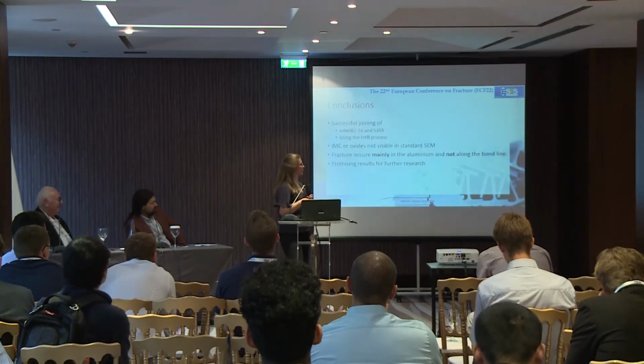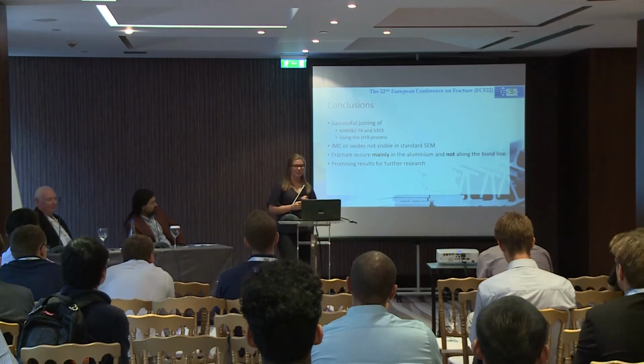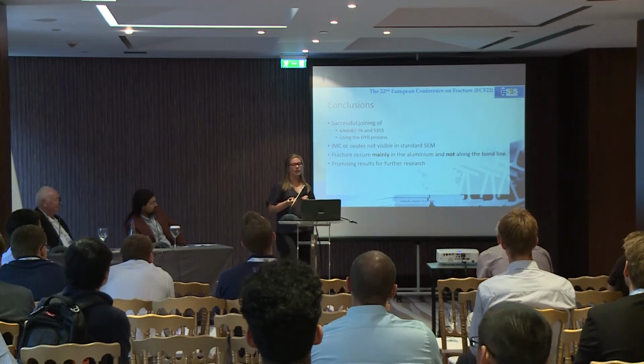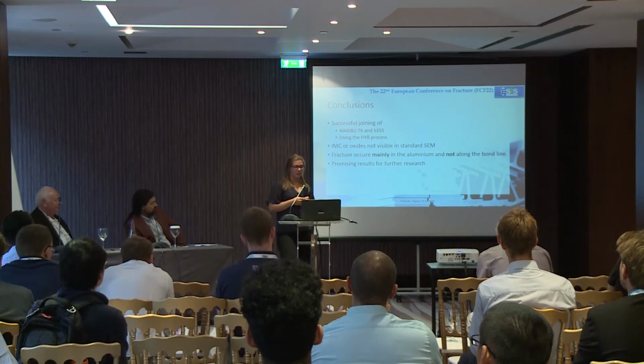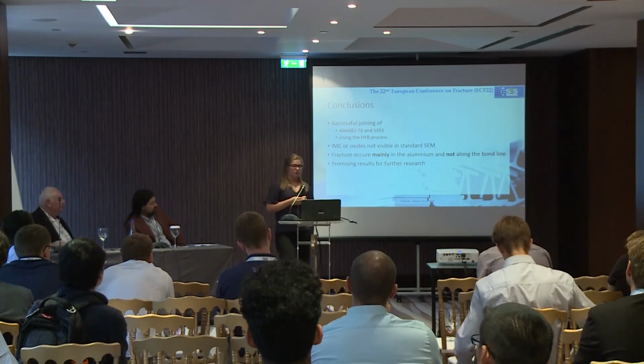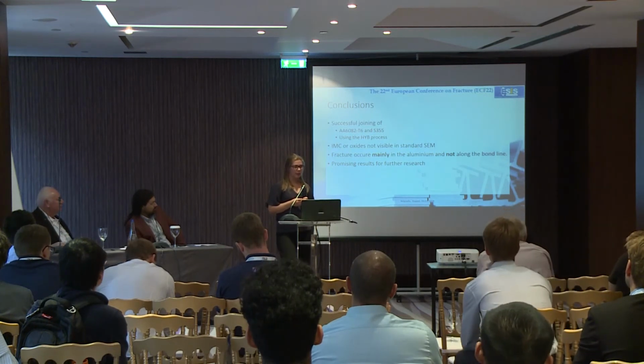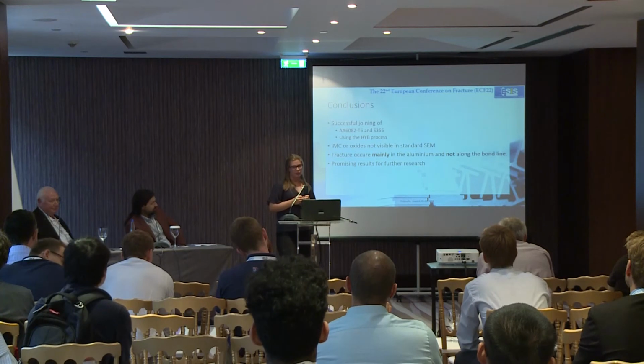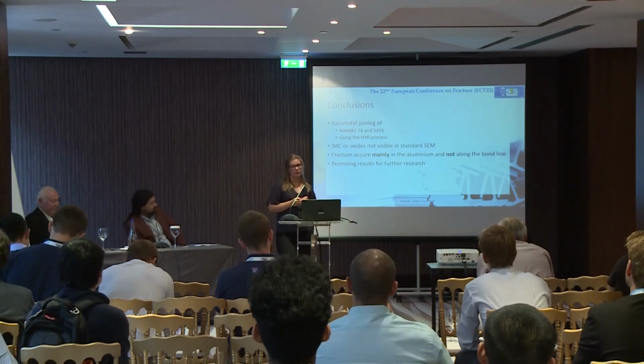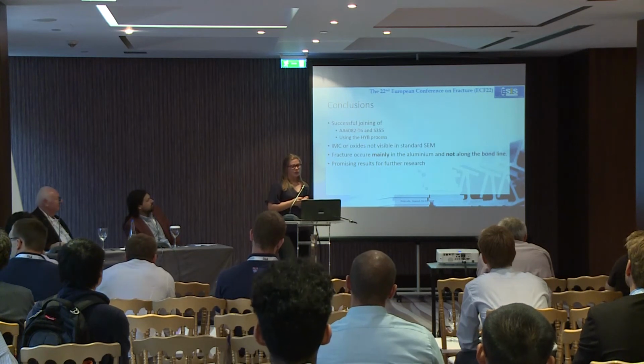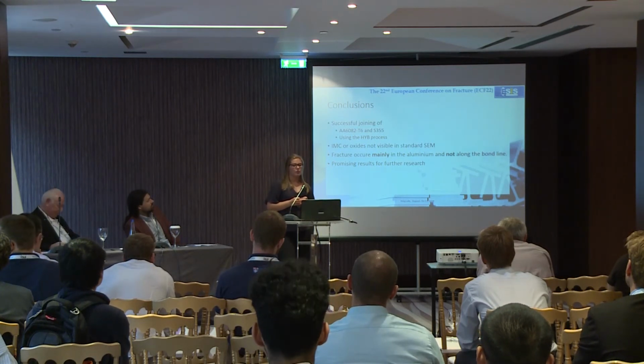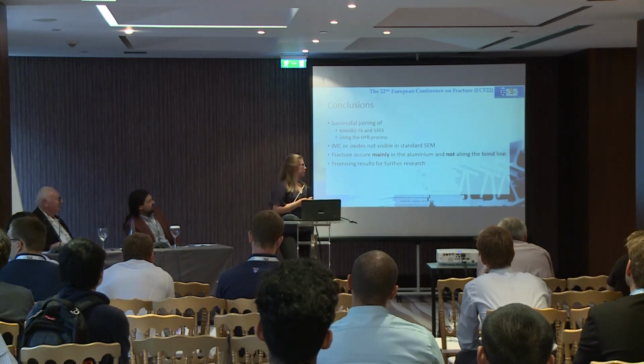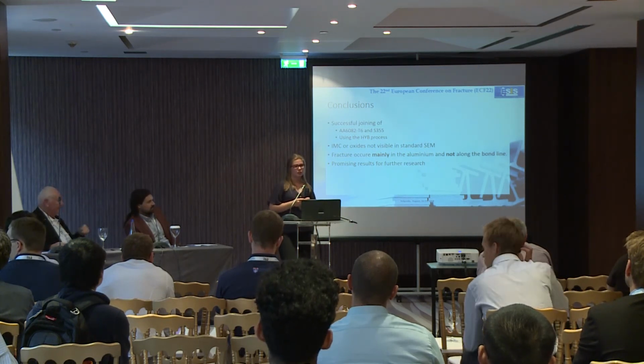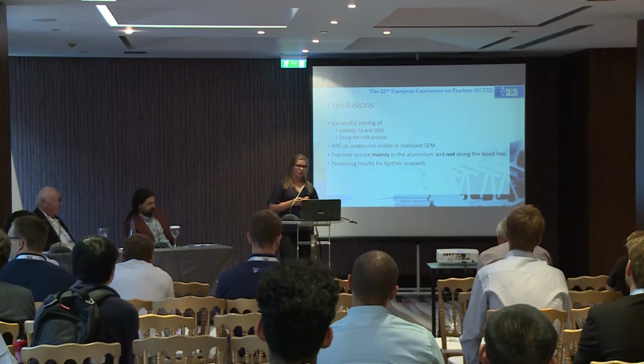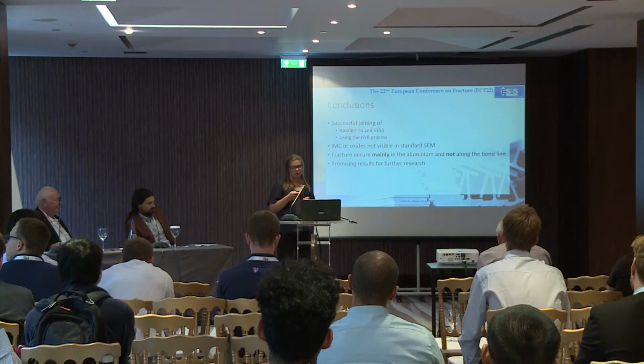So, the conclusion is that successful joining has been conducted between aluminum alloy 6082 T6 and structural steel 355 using the HYB process, and there are no signs of intermetallic phases or oxides in a standard SEM analysis. And fracture occurs mainly in the aluminum and not along the bond line, which is also encouraging for further research on this topic and the use of the HYB process for dissimilar joining. So, yeah, that was it.